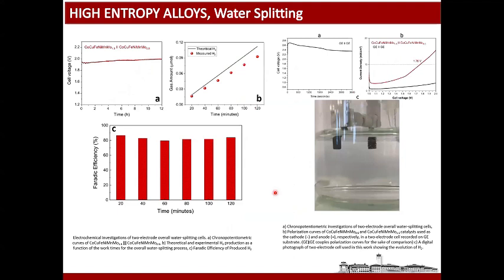So then we constructed the whole cell, complete cell, by using molybdenum 1.5 composition and the molybdenum 0.5 composition, and then we tried the overall water splitting in the cell. So the cell voltage is around 1.9 volts, and the Faradaic efficiency is around 85, close to 90%, and the measured hydrogen amount is close to the theoretical amount. As you see, the cell voltage decreases in this case, but over 100 hours, it is actually 100 minutes, it is quite stable, and it produces the hydrogen and oxygen at the same time. So it works well as an overall water splitting reaction.